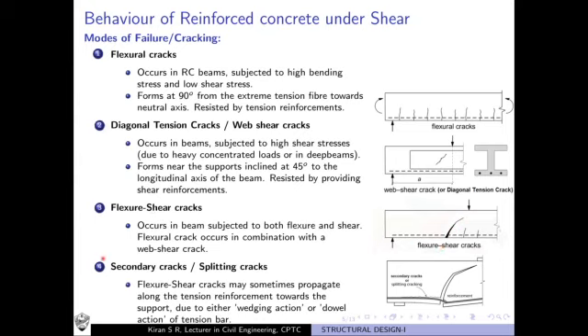Okay. Now coming to the fourth case of crack, which we call the secondary crack or splitting crack. You see, we have a flexure shear crack here. In addition to this crack, there occurs cracking or splitting along the tension reinforcement provided. Okay, along the tension reinforcement provided. And why does it happen? The possibility for such cracking along the longitudinal bar is due to wedging action or dowel action. By wedging action, what we mean is that here the flexure shear crack has occurred and this crack has split the beam into two.